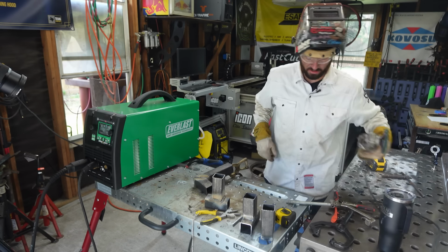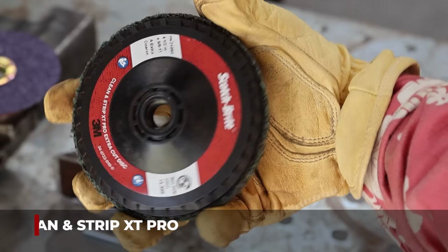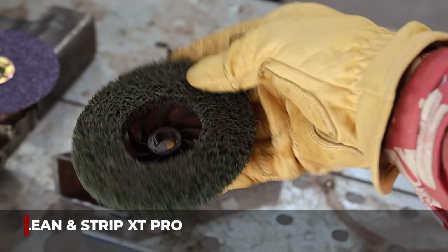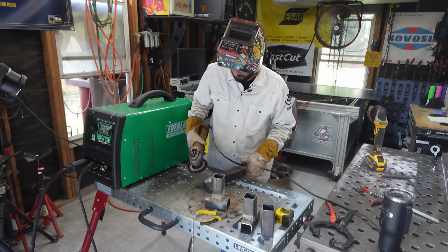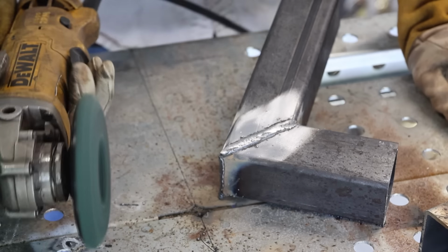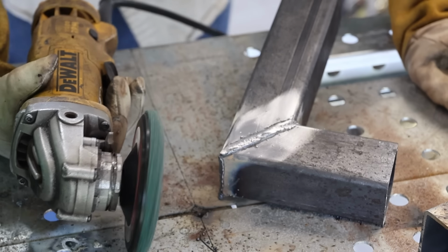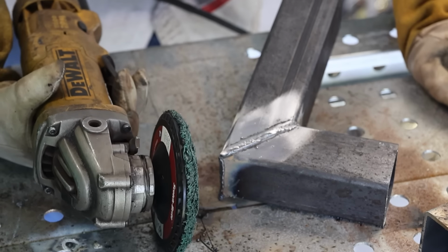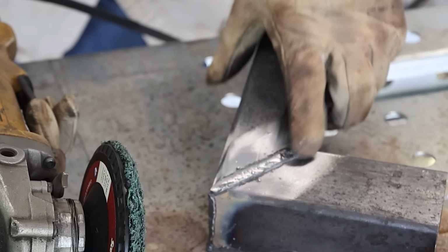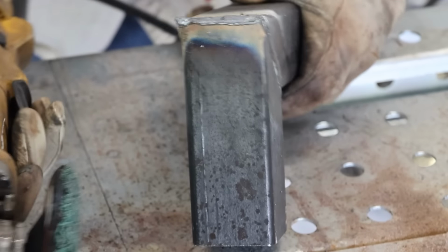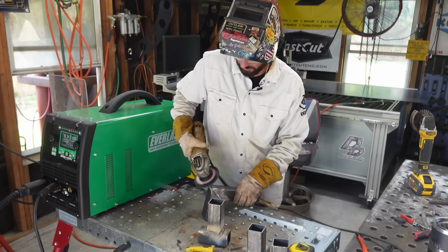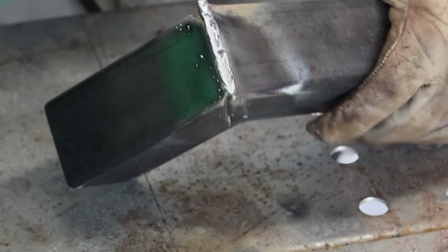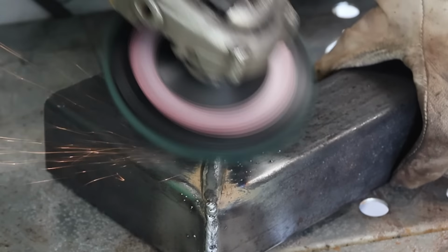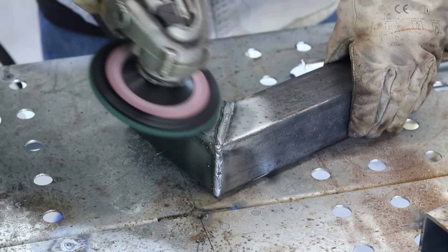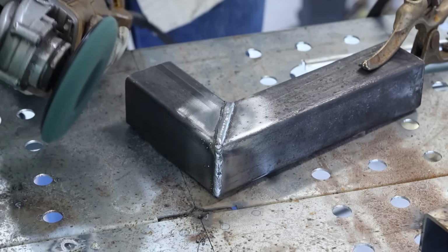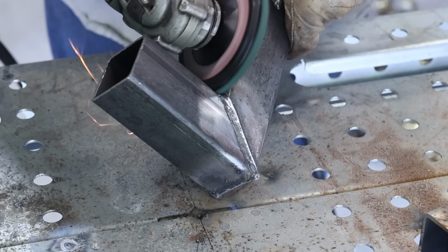All right, let's clean up some of this weld. You can use one of these Scotch-Brite wheels from 3M as a wire wheel too. It doesn't remove a whole lot of metal, and it doesn't leave a whole lot to the imagination. It's definitely going to clean up your weld really nice. We can see just a little bit in that crater, maybe a little bit of porosity. The back side, we can see we got a lot of porosity trying to run that weld downhill. That one there looks real nice. I like the way that one turned out.